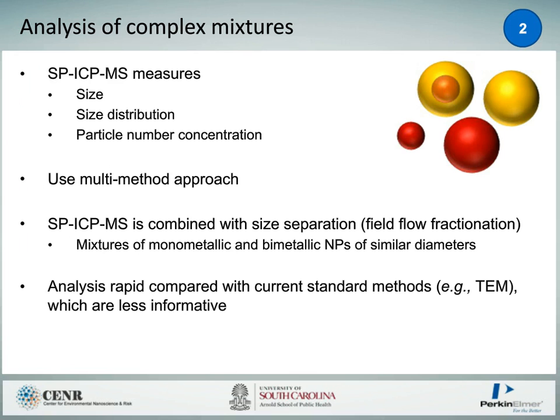So with that, I'd like to move on to the second application that we looked at. And here we were looking at the analysis of complex mixtures. So if we had bimetallic and monometallic particles in the same suspension, how can we tell the difference? Traditionally, this would be done with something like electron microscopy using EDS or STEM. Here we try to use FFF and single-particle ICP-MS as a much faster way of measuring this.